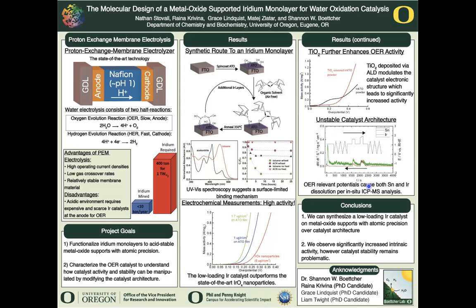But what can we conclude from what we learned so far? We have a lot of positive results, and we found you can synthesize a low-loading iridium catalyst on metal oxide support and be atomically precise over the nano architecture of the catalyst, adding different metals to tune electronic structures and increase activity significantly. And further, we observed significantly increased intrinsic activity compared to the state-of-the-art iridium oxide nanoparticles. However, the stability remains a problem.